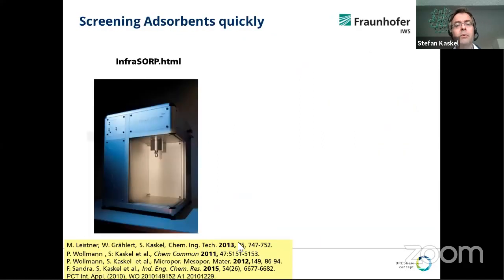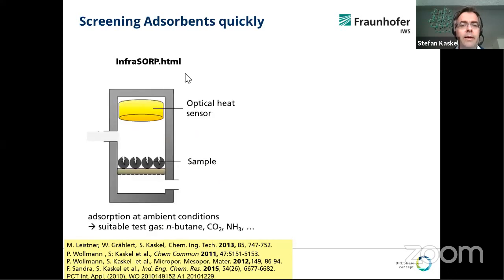So I was always annoyed because my students took so much time to measure isotherms. There was always a queue in front of the adsorption instrument. And therefore, we also tried to develop some adsorption methodology, some instrument. This is the so-called InfraSORP technology developed in cooperation with Fraunhofer IWS. It's a very simple measurement which allows you to measure an adsorption experiment in 5 minutes. And it is based on the heat of adsorption, because whenever an adsorbent adsorbs a molecule, basically heat is released because adsorption is always exothermic.